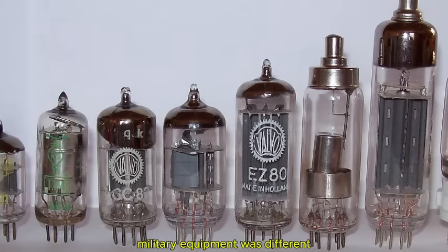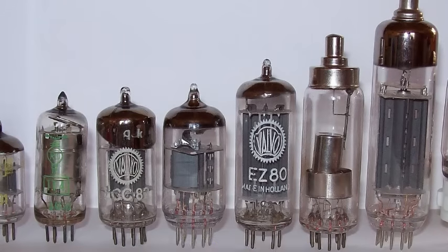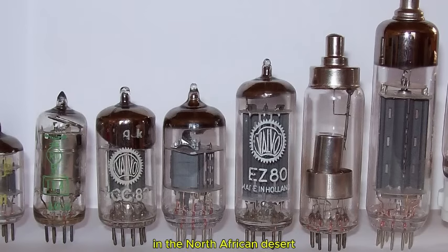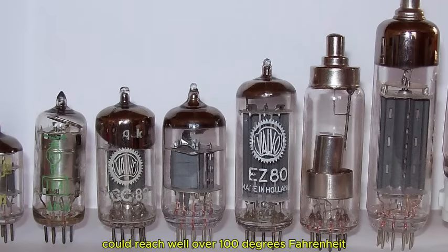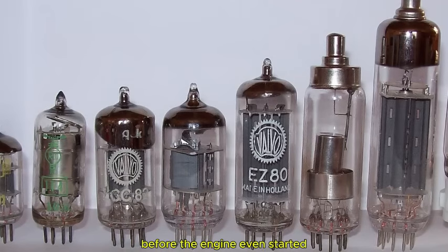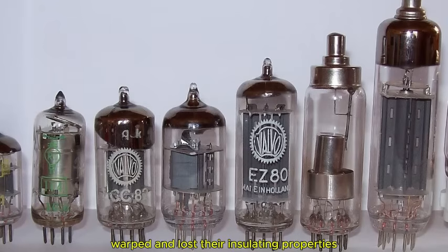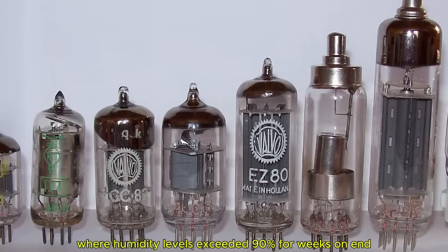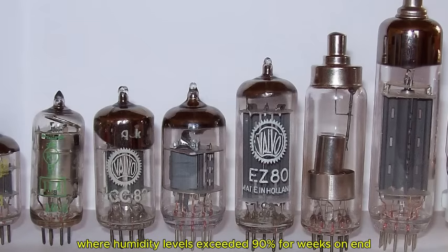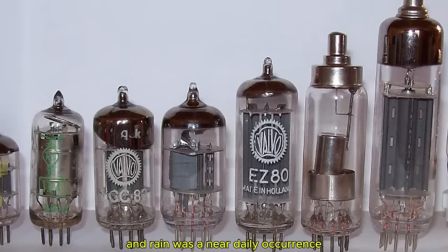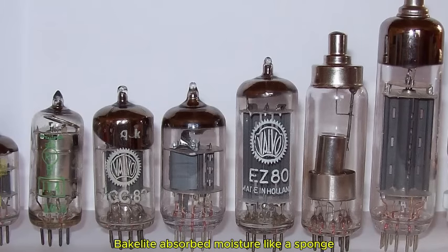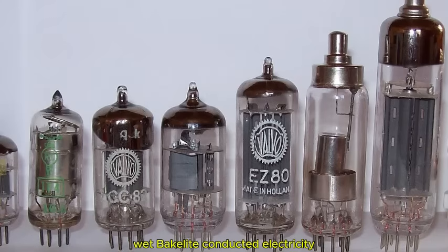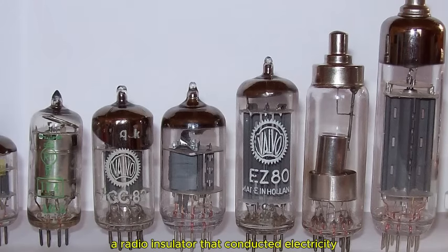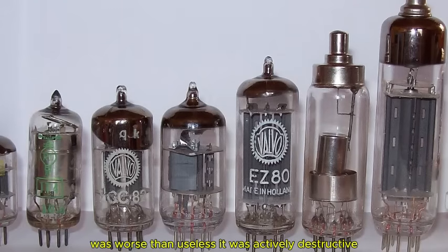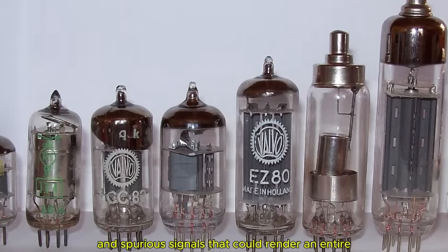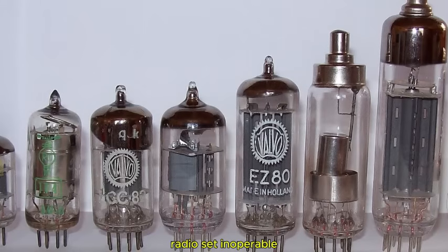Military equipment was different. Bakelite softened at high temperatures. In the engine compartment of a tank in the North African desert, where ambient temperatures could reach well over 100 degrees Fahrenheit before the engine even started, bakelite components warped and lost their insulating properties. In the Pacific, where humidity levels exceeded 90% for weeks on end and rain was a near-daily occurrence, bakelite absorbed moisture like a sponge. Wet bakelite conducted electricity. A radio insulator that conducted electricity was worse than useless. It was actively destructive, creating short circuits and spurious signals that could render an entire radio set inoperable.